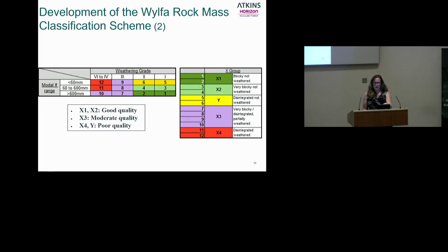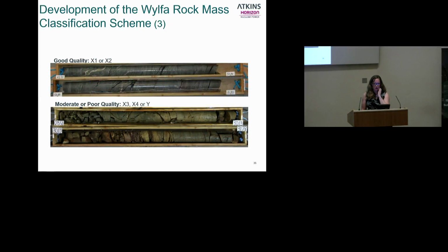Look at the colours here, because you'll notice in later slides. So the green is generally a good colour, good quality rock, and the purple and red is the poorer quality rock. A slide just giving you an idea. So the top photo is what we generally are finding as good quality, only slightly weathered, maybe fresh, fracture spacing of more than 60 mil. Bottom photo is moderate to poor quality, so less than 60 mil spacing and is moderately to highly weathered.